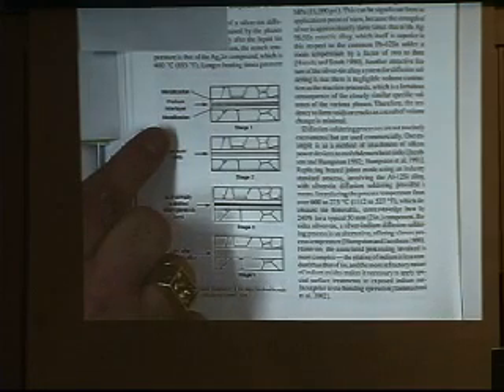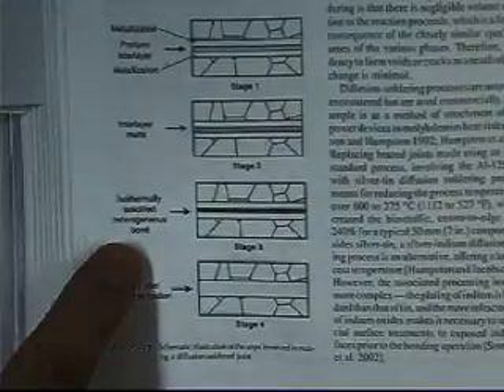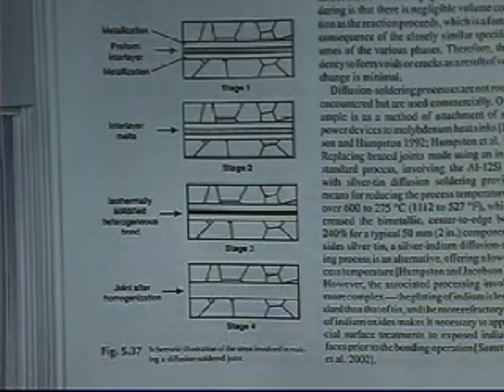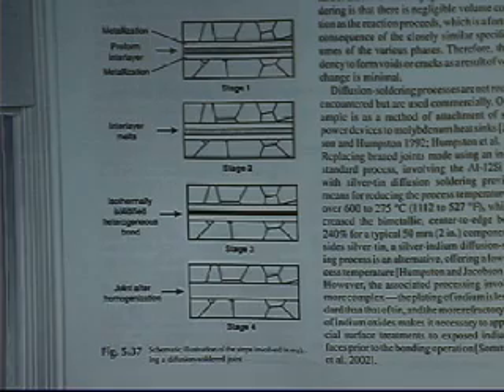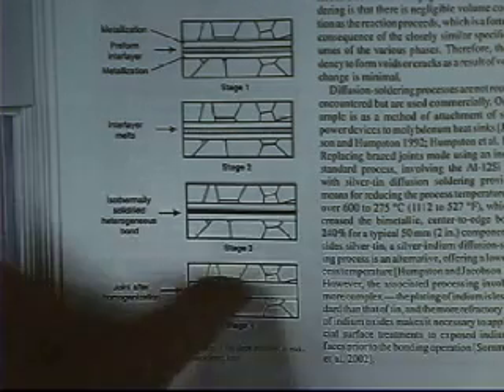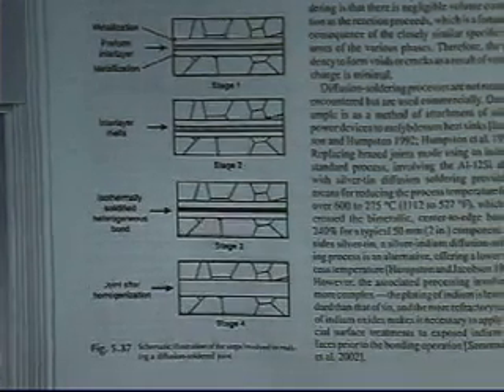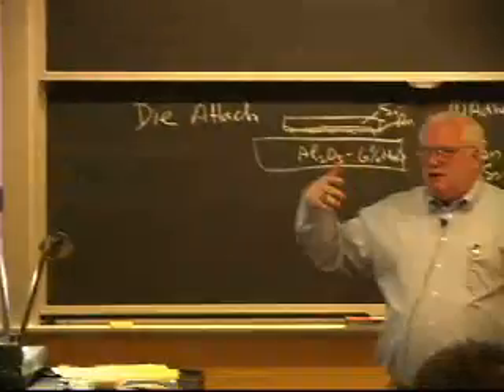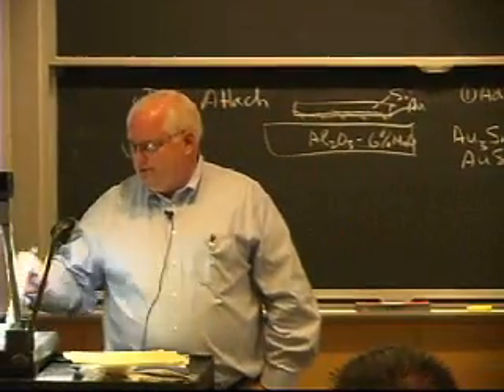They kind of took that out of the old welding handbook and adapted it for soldering, where you basically put in this case, they say metallization, a preformed interlayer. The interlayer melts, isothermally solidifies, a heterogeneous bond. If you hold it there long enough, you get a homogeneous bond. Well, in this case, this is a TLP joint, but it doesn't have the properties of the material on either side because it says homogenization, but it's still a joint layer. And this is basically a solder joint. Over here, this is an intermetallic, so it doesn't have the same properties. So it does get into the specific metallurgy of the system that you're talking about, okay?